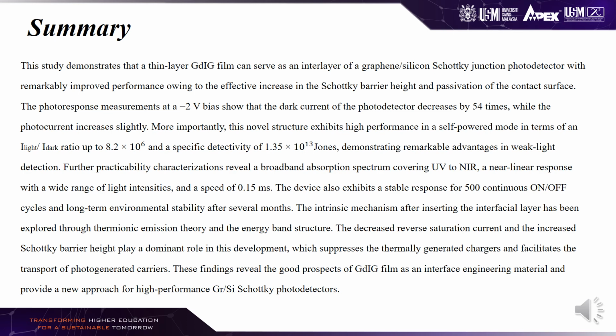The photoresponse measurement at a negative 2-volt bias shows that the dark current of the photodetector decreased by 54 times, while the photocurrent increased slightly. More importantly, this novel structure exhibits high performance in a self-powered mode in terms of a light current to dark current ratio up to 8.2 times 10 power of 6 and a specific detectivity of 1.35 times 10 power of 13 Jones, demonstrating remarkable advantage in weak light detection.